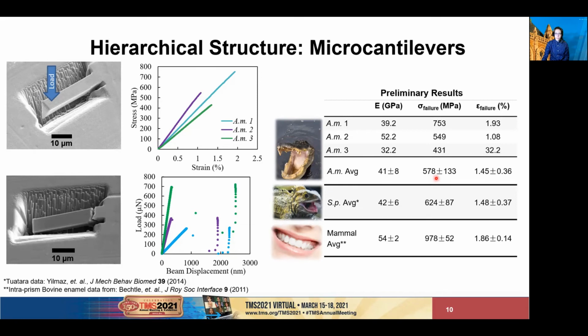These values line up quite well with the reported values from a microcantilever test in the prismless enamel of the Tuatara lizard, though ours had greater variance due to poor dimensional control. Compared to the intraprismatic enamel of mammals, that is, the hydroxyapatite nanocrystals within a single rod, prismless enamel is weaker and more flexible. This is probably due to the higher protein content suggested by Raman. All three of these microcantilevers were located in that middle enamel region, so the properties should be pretty close to each other.